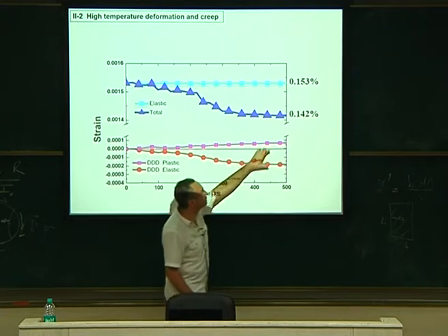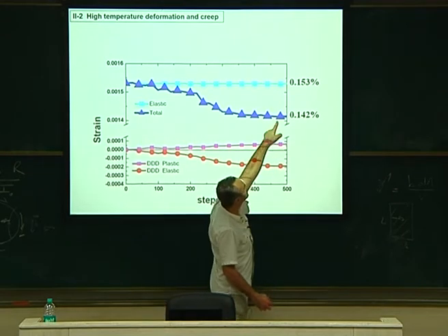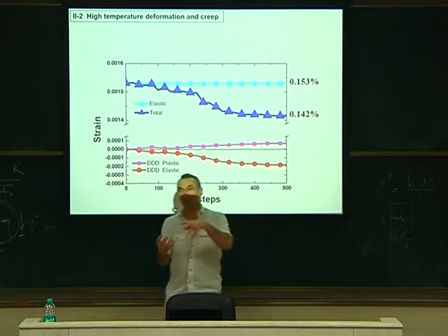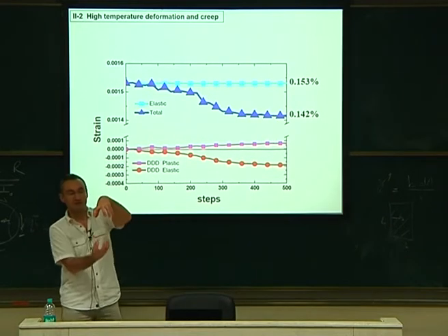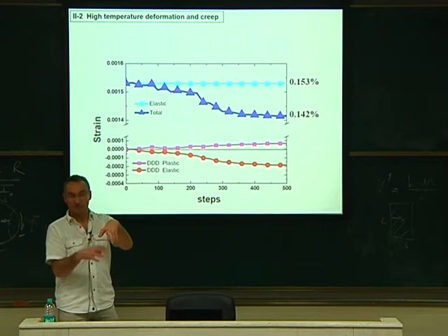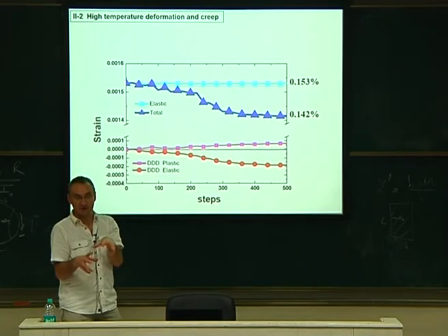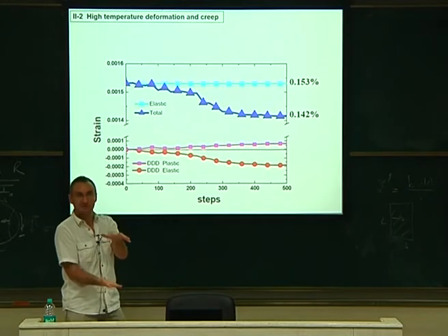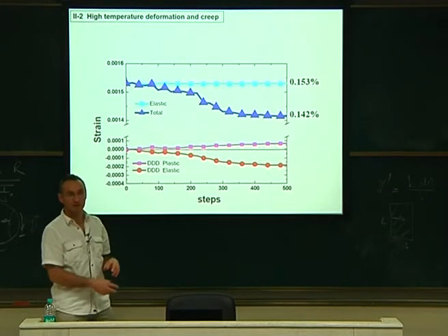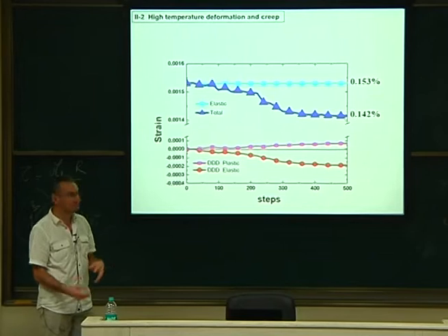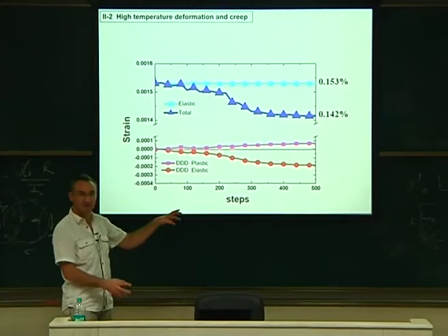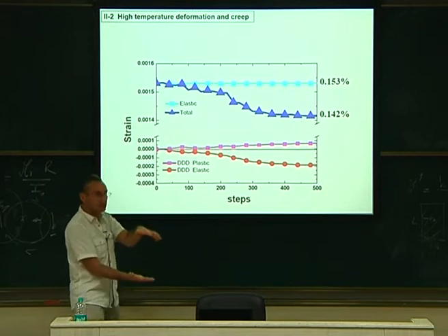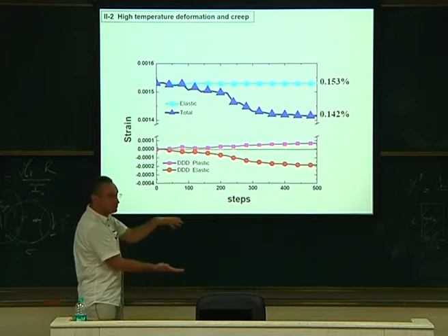So because of that, globally, you have a contraction. This is done here. You have this plus this, which is negative. So finally, although you accommodate plasticity along the z direction, you have something which is happening in the code. The dislocations interact, and they generate a stress which is attractive and which is compressing the z-axis. So now we'll have a look at why it is like that. What is the origin? But you get the idea? Plasticity is okay, but elasticity wants to shrink the horizontal channel.